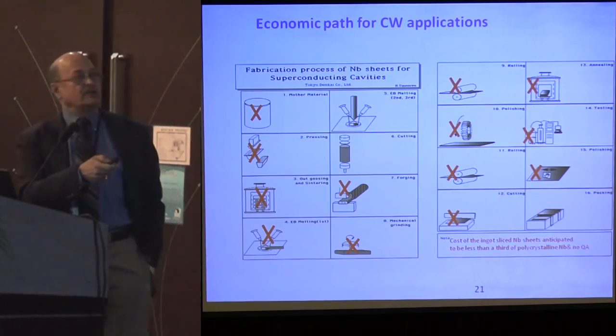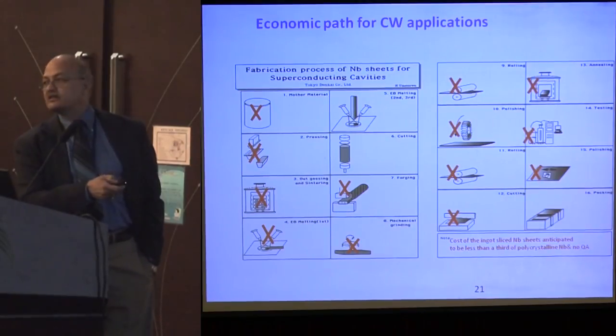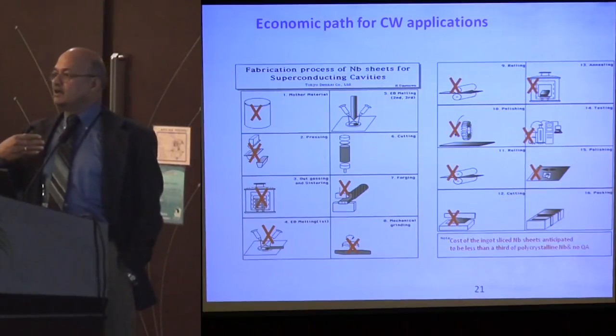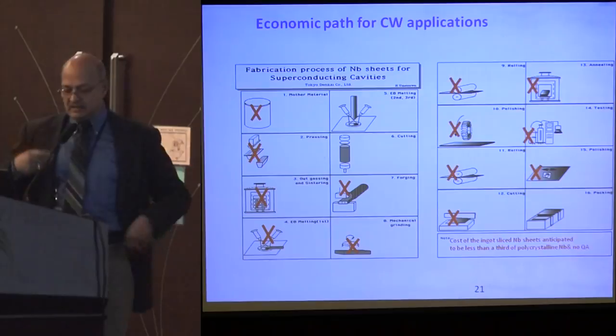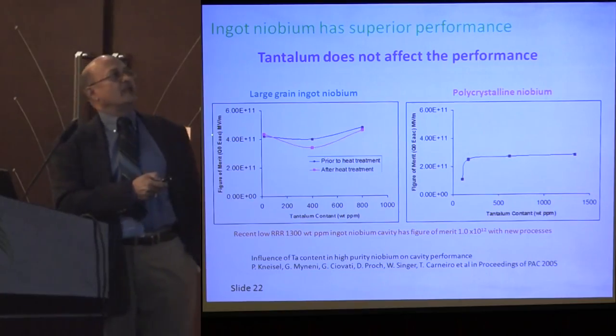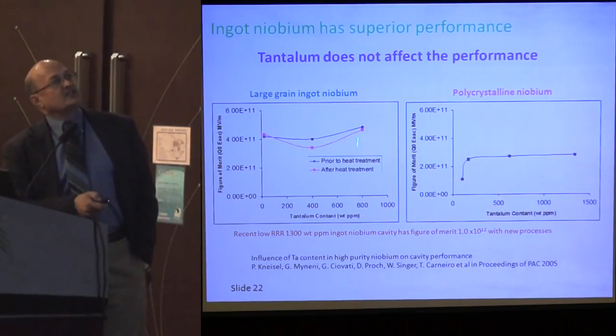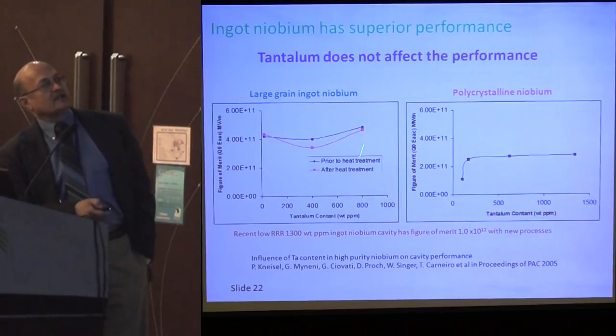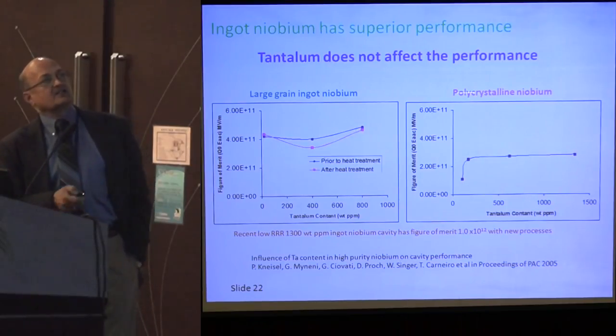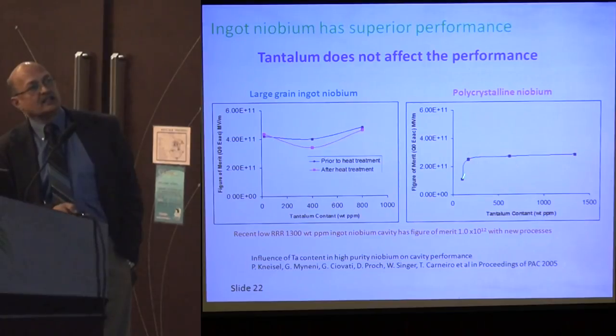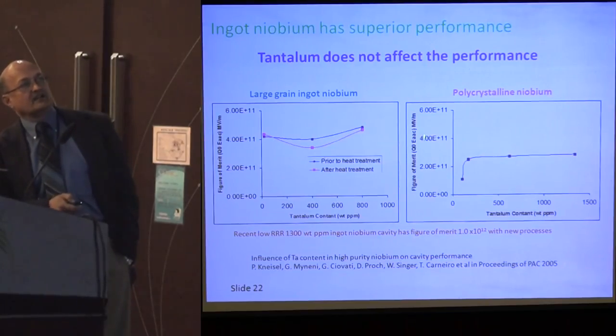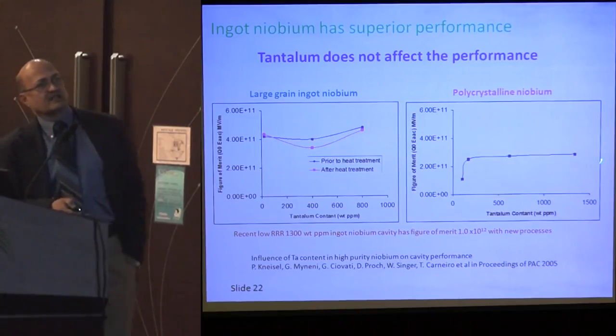So if you go to the ingot niobium route, basically you're eliminating most of the steps. You take the ingot that is coming from here, you slice it, and you can use it. As a result, you can save a lot of cost, and also the efficiency of these structures is much higher. We defined something called the figure of merit, which is a product of the quality factor and the gradient where it thermally breaks down. For large-grain ingot niobium, with a tantalum content up to 800, there's not really much difference. Whereas in polycrystalline niobium, if you take the low-tantalum-content niobium, the figure of merit is not as high compared to the tantalum content of about, I think here, 1375.